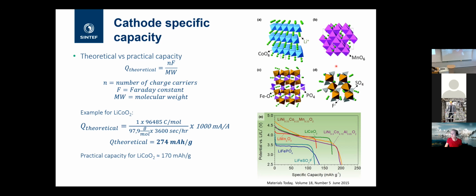If you look at some of the other structures that I've shown here, and this is important, I'm going to come back to this. This one up to your far right is a lithium manganese spinel, shown in the red line in the figure. The lithium manganese spinel has lithium diffusion in 3 directions because it's a channeled structure. Lithium iron phosphate, which is the blue line here, shown in figure C, also has a channel structure, but it's only one dimensional, like tubes going down. So it has a bit slower conductivity, as we're going to look more into.